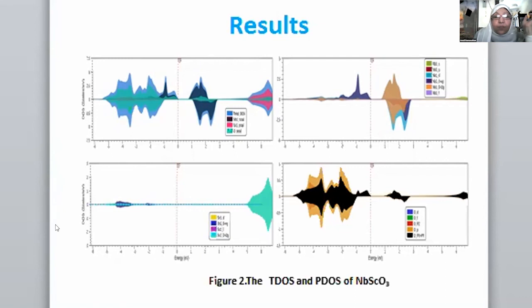I think the first one is the niobium, and this one is the scandium, obviously, because as my results showed, this is hardly doing any, there is very negligible contribution from scandium. And then we are having the oxygen. So the first one is the total. This is the partial atom ones, the niobium, the transition metal, on the right corner. And since you're seeing it, you all will appreciate it much better than me at this moment. Of course, I've already done the results.